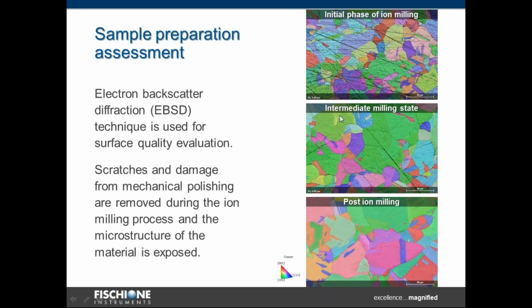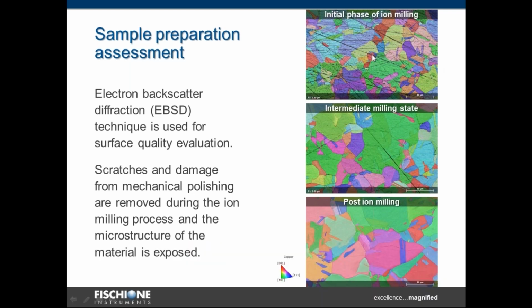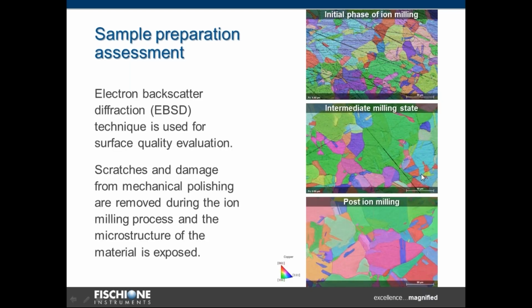As you can see here on that example, the initial phase of ion milling, we still see some scratches from mechanical polishing and induced deformation. While we mill, we remove the scratches, we remove the deformation, and post-milling image show a native structure of the analyzed material. So that is the reason that we will show a lot of EBSD data.